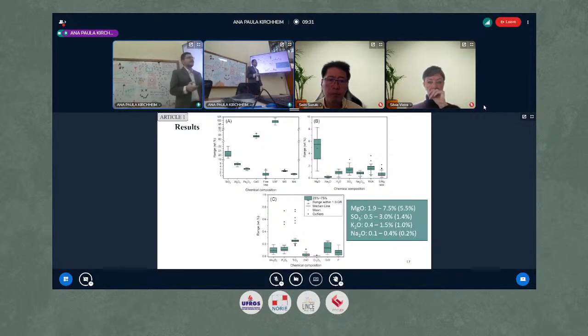And here I highlight the phosphorus, where some clinkers have 0.7%, and the titanium almost 0.8%, due to raw material impurities or due to co-processing. And here we have the mineralogical composition of these clinkers, and we have a variation of alite between 56% and 73%, belite between 4 and 24.5%, C3A between 2.3 and 7.7%, and C4AF from 7.4 to 13.1% of the clinker. So we have a great variation in clinker mineralogy as well.